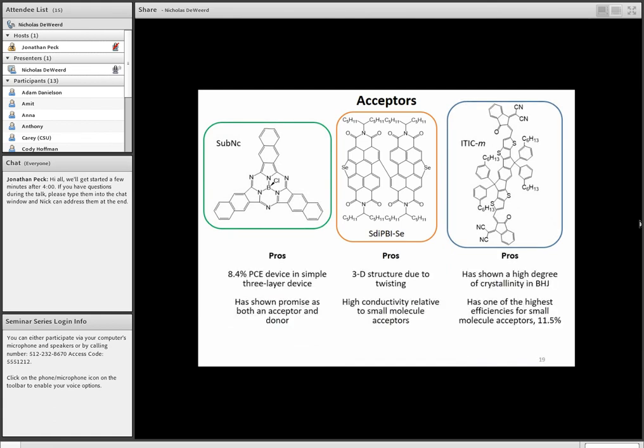So starting from left to right, on the left we have a pretty interesting small molecule acceptor. That's mostly because this sub-NC, as well as two of its derivatives, were used together in a tandem device to generate an 8.4% efficiency tandem with minimal optimization. So that's really promising. That means that you don't have to worry about all the nuanced morphology control between different types of acceptor molecules. Being able to do this and then utilize this type of acceptor, and it targets different sections of the absorption spectrum of the solar spectrum, means that you could, in theory, generate a tandem device a lot easier, with less morphological control being required and fewer studies.